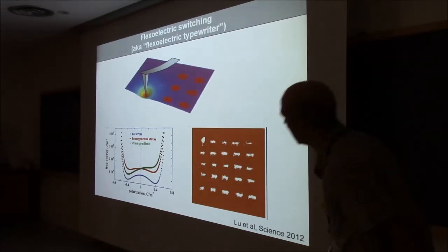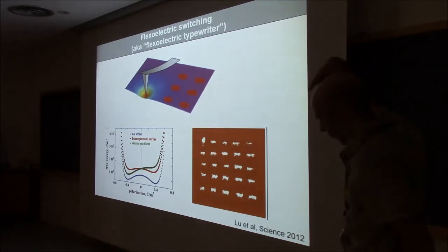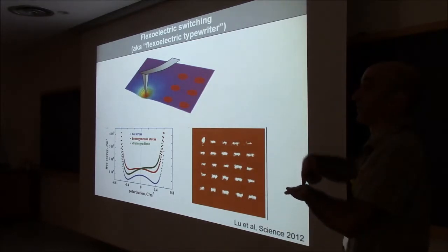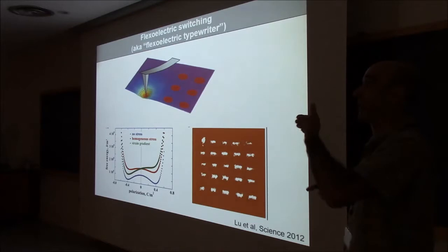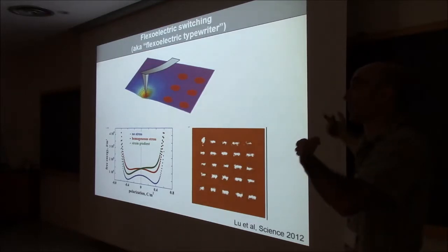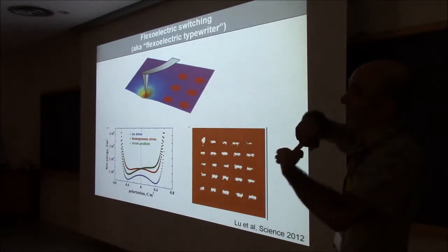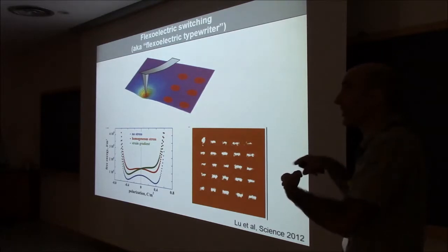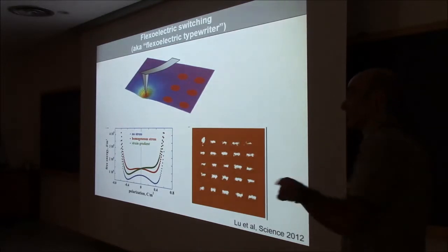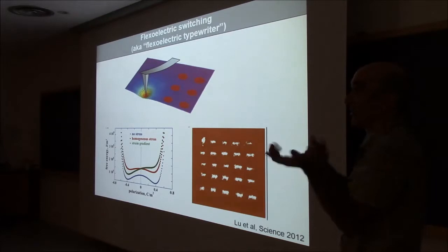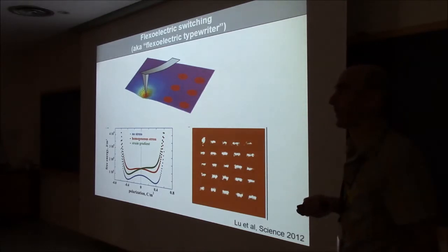I think the way to do this is not to do out-of-plane polarization, but to do in-plane polarization. So if you have something that is in-plane polarized, I can drag my tip towards the right, or drag my tip towards the left, and so that flexoelectric writing will write the polarization in plane that way or that way. That way you make it reversible.